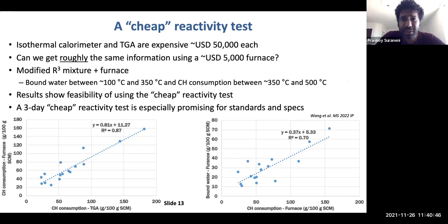Now, one of the major concerns with some of these reactivity tests is they're expensive. An isothermal calorimeter and TGA together cost $100,000 US, which is a lot of money. So we asked ourselves the question: can we get essentially the same information using a furnace, which costs about 20 times lower? And luckily for us, the answer is yes. So we take the same modified R3 mixture and we put it in a furnace. We measure bound water between 100 and 350 degrees and the calcium hydroxide consumption between 350 and 500 degrees. And we find that there is actually a pretty nice correlation. The calcium hydroxide consumption measured from the furnace matches pretty nicely with the calcium hydroxide measured from the TGA.